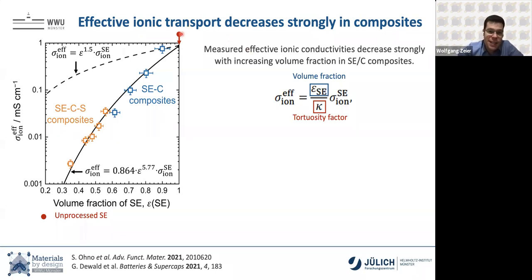The first thing that we see is actually very interesting. When you make these composites, you usually ball mill them. And here we have a fast ionic conductor, and when we apply the processing conditions that we use to make composite electrodes, the ionic conductivity drops, which is a little bit counter to the statement I said earlier that ball milling is good. So let me amend that statement. Ball milling is good if you want to make a fast ionic conductor, but if you keep ball milling it, you're going to make it worse.